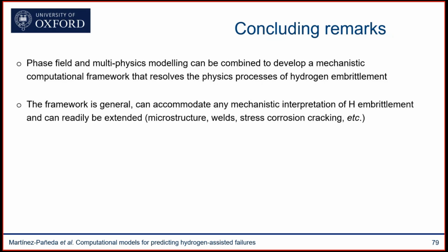This means that our model is dependent only on parameters that have a physical meaning that we can measure in our lab. And our model can be quite general. So whether you agree on my interpretation of hydrogen embrittlement or not, you can use this to your benefit. And we have seen other groups using this, for example, to incorporate HELP mechanisms or a combination of decohesion and HELP mechanisms. And you can incorporate this method very quickly to other phenomena.